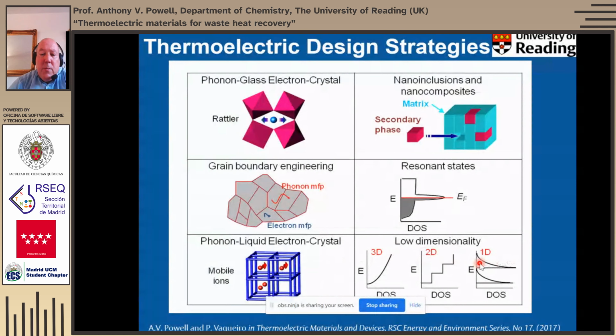And finally, something that was first proposed by Hicks and Millie Dresselhaus, probably over 20 years ago now, is that if you decrease the dimensionality of a solid, then you actually introduce more discontinuities into the density of states. And given that the Seebeck coefficient is proportional to the derivative of the density of states at the Fermi level, if you can introduce discontinuities and then fill up to that point with electrons, then it's possible to get enhancements in Seebeck. I think to a certain extent the jury is still out on that one, because when you go to low dimensional systems, you also introduce some interfaces between layers and so on, and that can also affect the thermal conductivity.